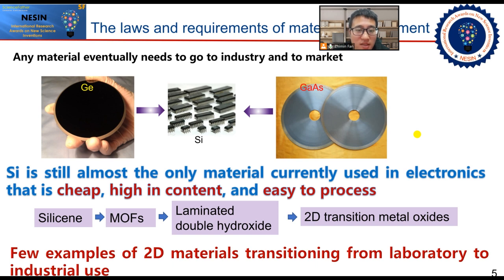For example, in the semiconductor industry, the electron mobility of germanium is better than that of silicon, but silicon is still almost the only material in electronic products because it is cheap, high in content, and easy to process. In other words, the law and the requirements of material development are still to be cheap, high in content, and easy to process. Therefore, both graphene and the subsequently emerging two-dimensional materials are currently facing the dilemma of transition from the laboratory to industrial applications.